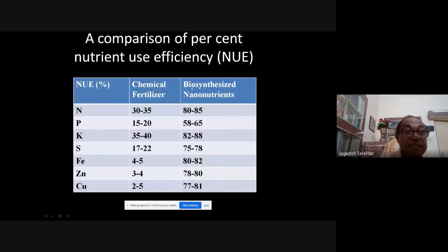You can see that use efficiency. This is where I compare our biosynthesis nanonutrient with chemical fertilizer. You know, nitrogen use efficiency, if you put 100 kg to your field, you will get 30 kg effect. Only 30 to 35% use efficiency for nitrogen. But in case of biosynthesis nanonutrients, we found 80 to 85% use efficiency. That means you may expect 2 to 2.5 times more use efficiency. Phosphorus, only 15% use efficiency. So if you use nano, you can increase use efficiency 4 times.